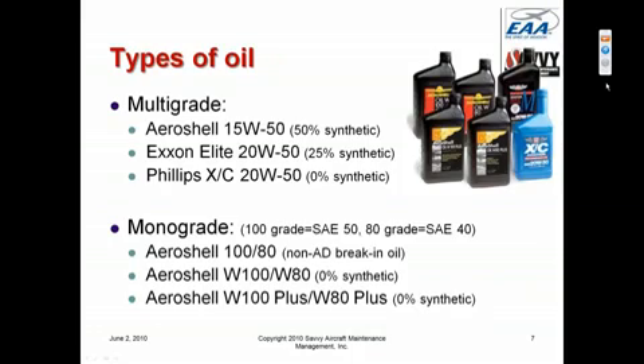Moving on to types of oil, we have both monograde and multigrade oils. This list of 6 oils is the most common, the most common oils used in the U.S. In the multigrade stack, the most common oil that's used today in the general aviation fleet, and actually the one that I dislike the most for reasons that I will tell you in a bit, is Aeroshell 15W50. It's a multigrade oil that is composed of about 50% synthetic stock, something called polyalpha olefin, which is a synthetic oil, about 50% mineral oil made from dead dinosaurs, and a bunch of additives, including viscosity index improvers that provide the multigrade characteristic. We'll talk about all of these in following slides.